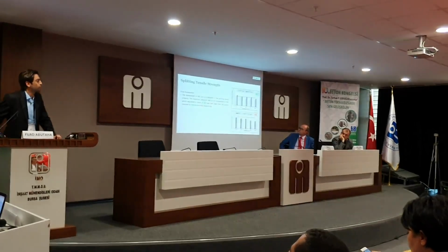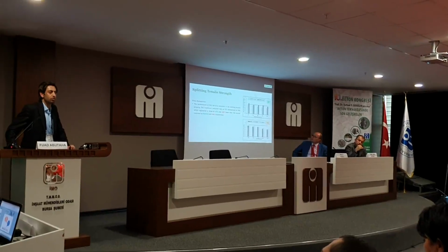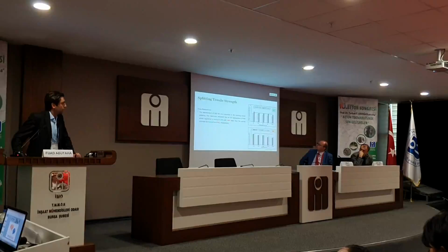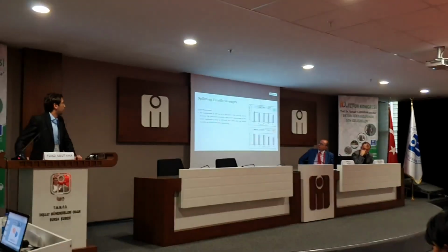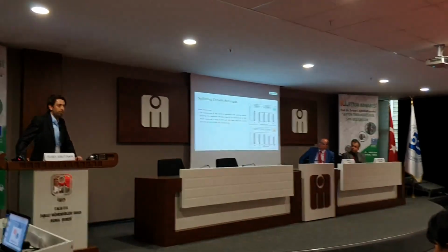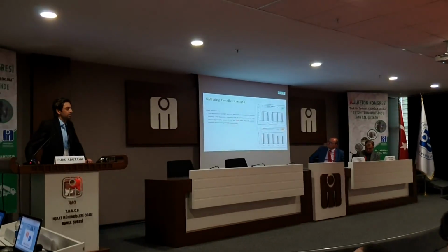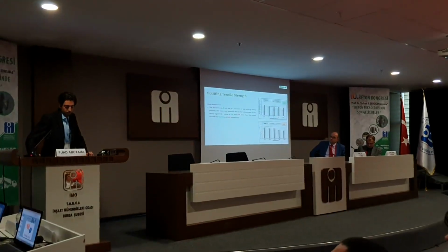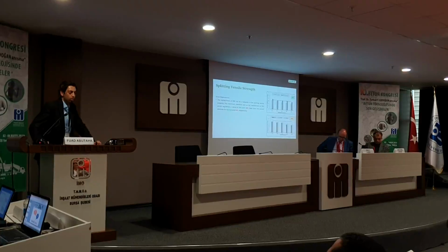The same trend was also found for the splitting tensile strength. There is a reduction when incorporating POC coarse aggregate. The higher the content of POC coarse aggregate, the lower the splitting tensile value, and the maximum reduction was at full replacement, which was 27% lower for normal strength and 32% lower for high strength than the splitting tensile of the control concrete.